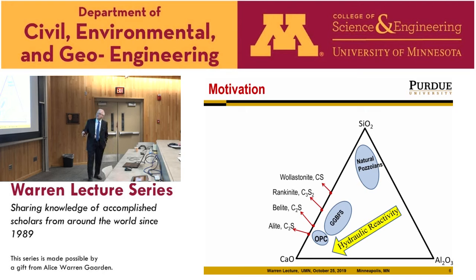And it turns out that you can actually make cement that contains those 2 non-hydraulic compounds at about 200 degrees lower temperature than you need for production of clinker that is associated with ordinary Portland cement. So instead of going to 1450 degrees, you can make it at 1250. You think maybe 250 degrees is not much, but it actually is a lot of energy. If you multiply it by the billions of tons that we are making, that actually is a big saving.